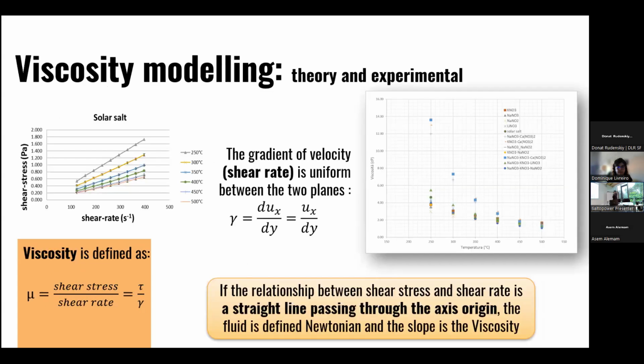Then we decided to determine the viscosity of all the mixtures that we reported with a rheometer. We performed a lot of tests on each mixture, just to be sure and just to decrease the experimental error. Here we reported the viscosity versus temperature, and I reported only the very easy formula that, as everybody knows, the gradient of velocity, called shear rate, is uniform between the two planes, and the viscosity can be defined as the shear stress on the shear rate.